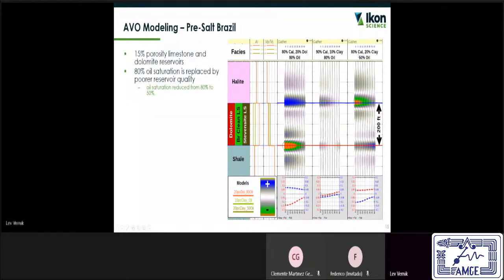Now, finally, we arrive at modeling an 80% calcite, 20% clay reservoir, poor quality reservoir, and still 50% oil. And you can see that there is a significant difference between this type of response and this type of response, or this type of response. So the conclusion here is that in each specific case, a geophysicist must do the modeling, presumably with good logs. If he doesn't have good logs, then I would encourage him to use rock physics models, such as I presented. And then you can relate the synthetic AVO signatures to the actual gather, CDP gather, amplitudes in the field, and then make a definitive conclusion.